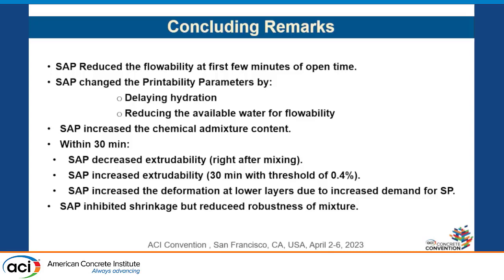And also SAP increased the deformation at the lower layers. That's a problem. Controlling superplasticizer in favor of the viscosity is an issue. But our recent results show that SAP can inhibit the shrinkage due to evaporation, but like I said, that is still something I'm concerned about, the reduced robustness of the mixture.